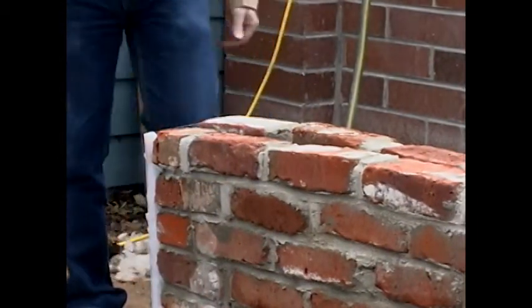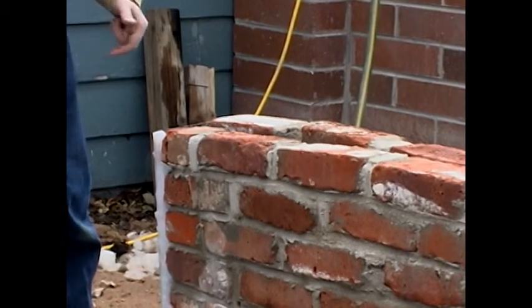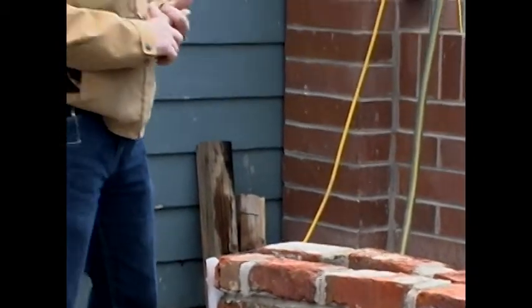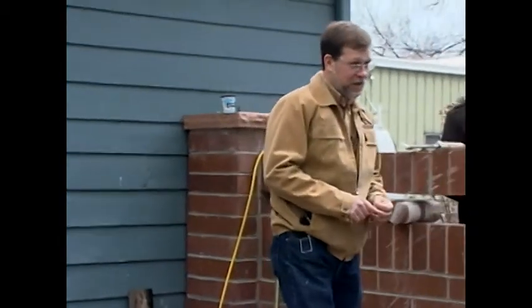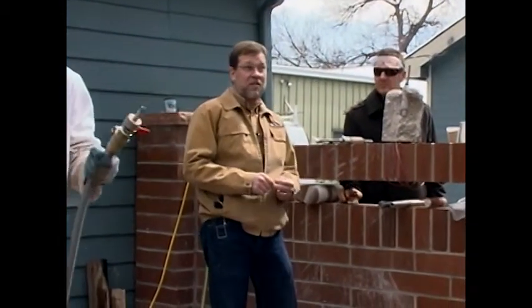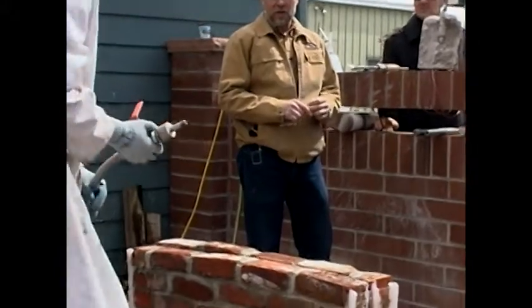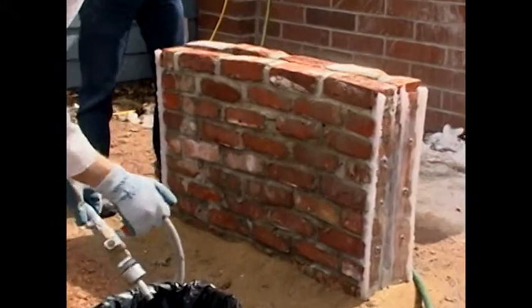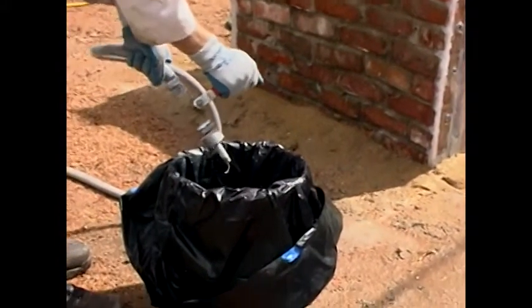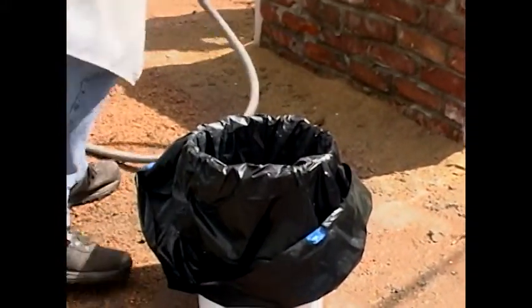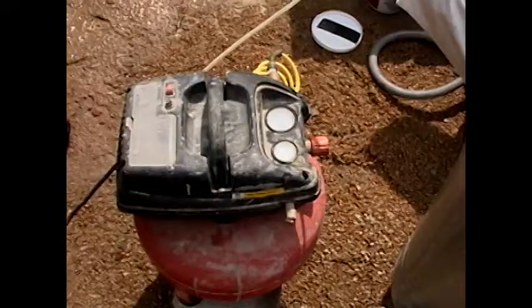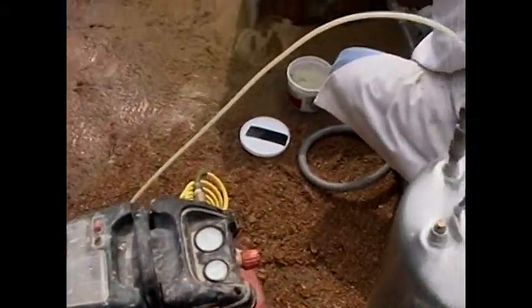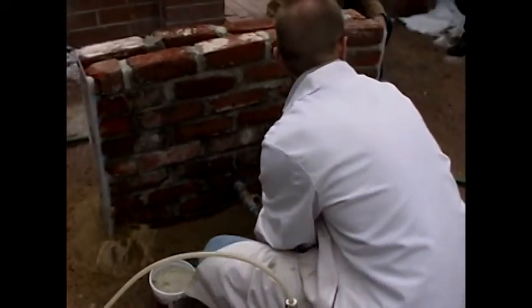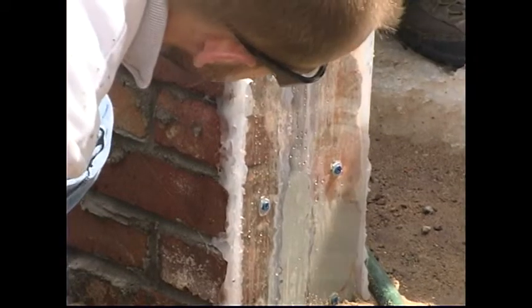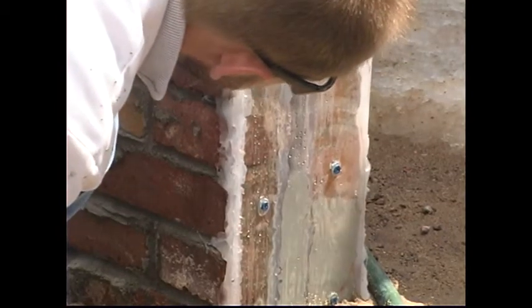So we have a pressure pot. Here in New York, we operate at low pressure, the injection 8 to 10 psi. So it's really different from concrete crack injection, which uses 1,000 psi, 1,500. You get the penetration through good flow, not necessarily high pressure. And we found high pressures can tend to segregate the material. They'll force the water right out of the mix, and things will clog up in the hose, and it's a problem.